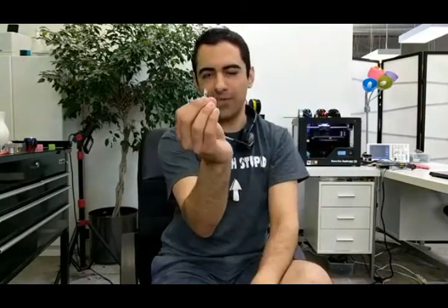actual filament movement. So if you load up 4, you definitely get an increase for a couple reasons. You have generally more surface area touching the walls. For each one of the channels now, instead of having one move really quickly, you can have 4 of them moving a little slower. You also get more extrusion force. You actually have pretty close to 48 pounds of force maximum if you're pushing with all 4 of them, which is why we have such an aggressive slot in the nozzle to keep it from moving. So that's a lot of energy, both force and heat. So you can get an enhancement, but if you really want this thing to cook,